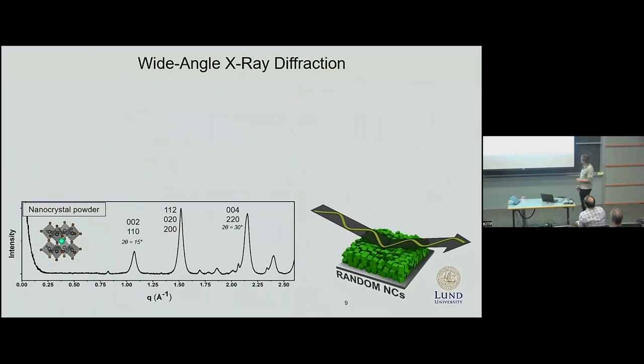When we looked at the control sample, that is a nanocrystal powder, we saw, as expected, reflections coming from the Bragg peaks of the orthorhombic perovskite lattice.